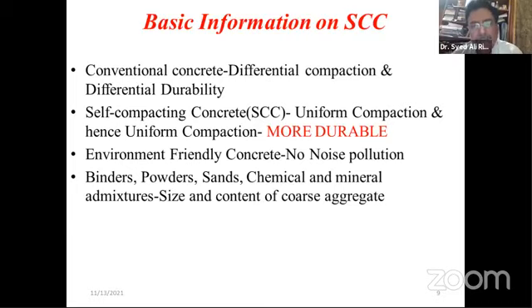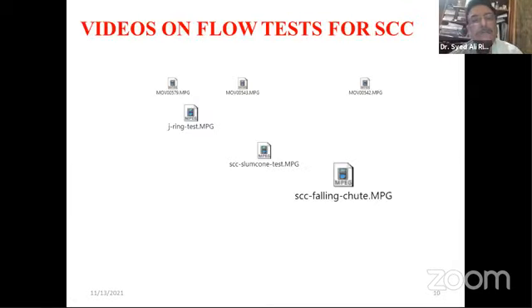But later on, when imaging techniques like scanning electron microscopes were invented and applied, it was evident that if the size of coarse aggregate is high, the thickness of the interfacial transition zone will be more, and that is the weakest link in the chain of a reinforced concrete structure. So we want to have a smaller size and a slightly lower content of coarse aggregate. Then I will try to show you some videos.